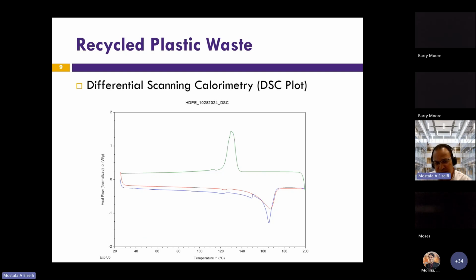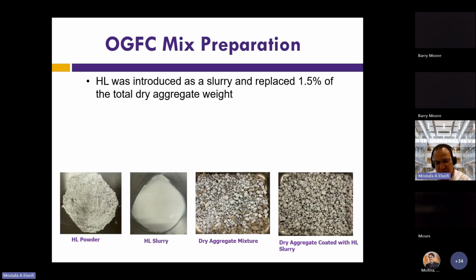We also did the differential scanning calorimetry to look at the melting point of the plastic, and it was around 167 degrees Celsius, as you can see from the blue peak at the bottom here. For hydrated lime, we used it as a slurry, which again is the preferred method to incorporate hydrated lime. So we mixed it with water at a ratio of 1:2, and then we blended it with the dry aggregate, as you can see in the picture at the bottom. And after the aggregate are adequately coated with the hydrated lime, we placed it in the oven overnight at 110 degrees Celsius.